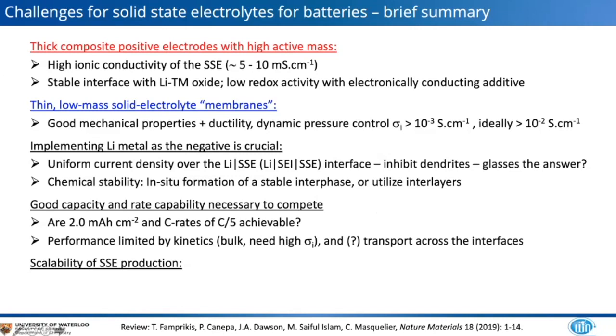So the first point is that thick composite electrodes with a high active mass are really necessary in order to compete with today's lithium-ion batteries. So that implies that we have high ionic conductivity of the solid-state electrolyte in the order of 5 to 10 millisiemens. And we have this stable interface that I mentioned and low redox activity with the additive.